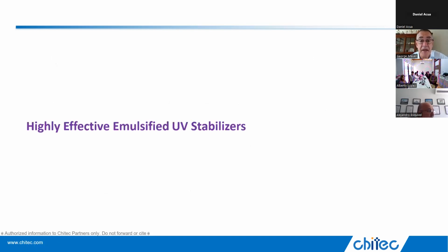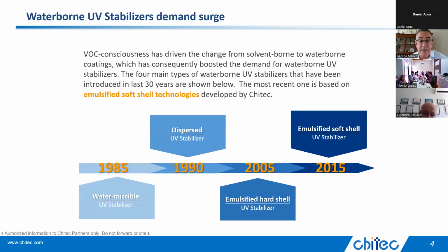We're going to go over some of the science behind it and the evolution of the waterborne UV stabilizers. Back in the 80s, Ciba-Geigy came up with a material, Tinuvin 1130, which is a water-miscible UV absorber. It's also sometimes used in solvent-borne coatings, although I don't generally recommend that as the best option. You just pour it in. Sometimes you need to use co-solvents to get it into the water. We'll see a little later on that has a bit of a problem, because since it likes water, that means it can wash out of your film. So that's the old technology, 1130.